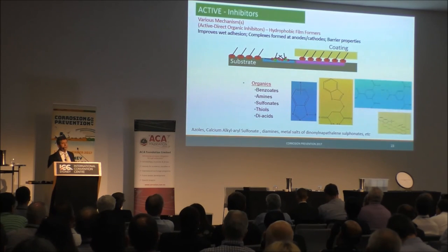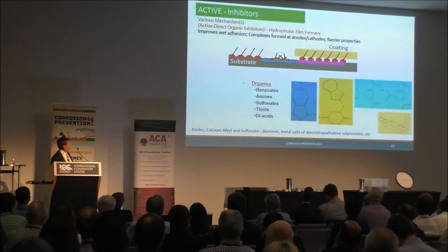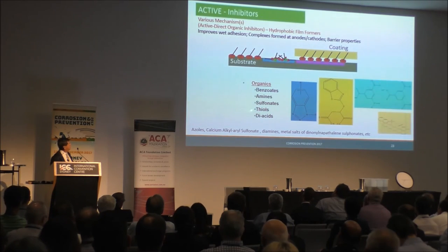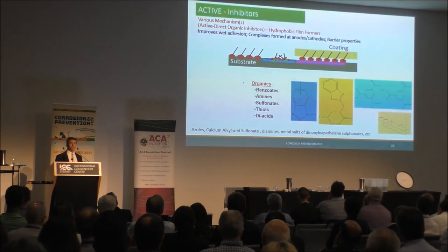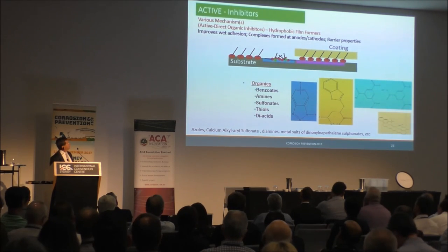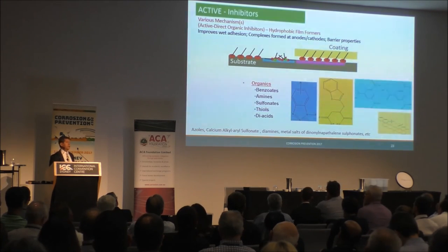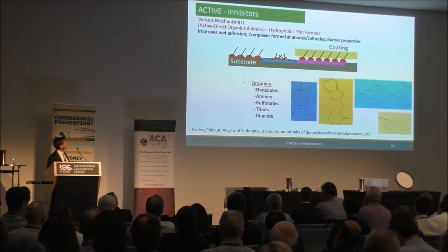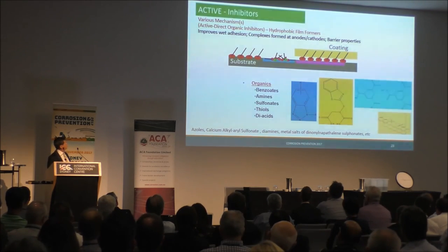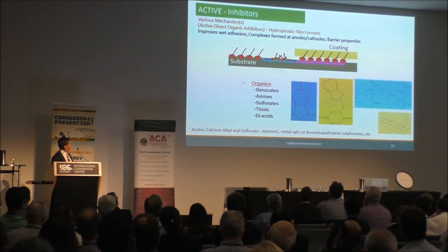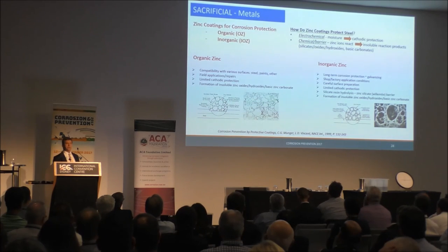But there's many other things that you can put into the coating in terms of corrosion inhibitive species. There's a plethora of organics that are added, you see here the list of them. And these all essentially form almost like a film formation on the surface of the metal, so that it slows down the rate of corrosion at anodic and cathodic sites. This is more of a kinetic type effect, really, rather than the thermodynamic effect of changing the chemicals in the system. So there's lots of opportunities here for designing coatings for corrosion protection.